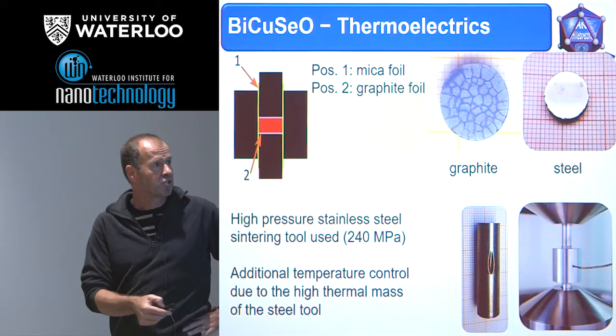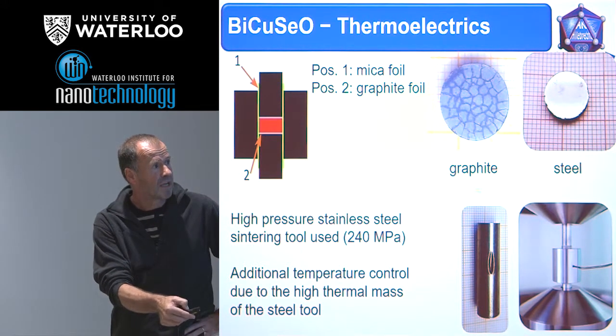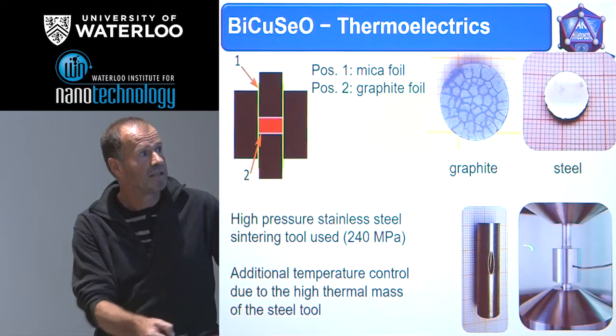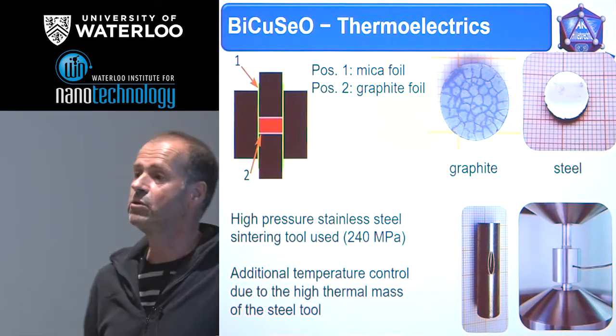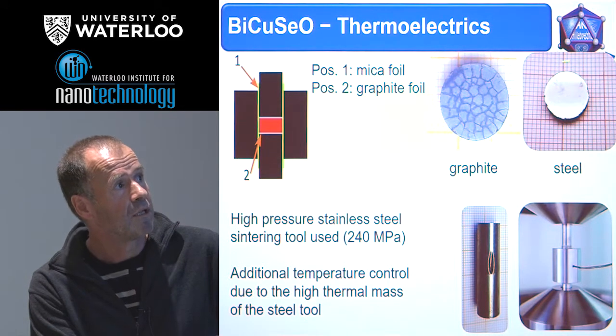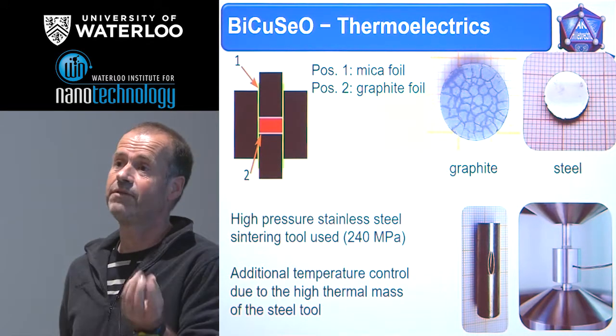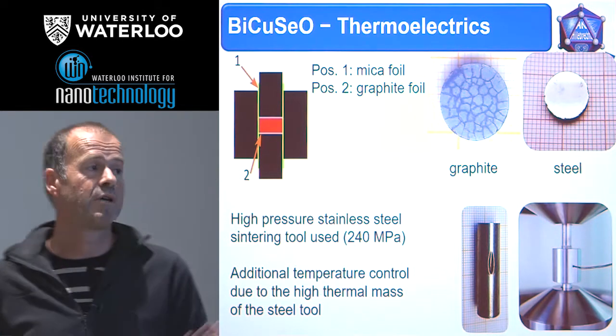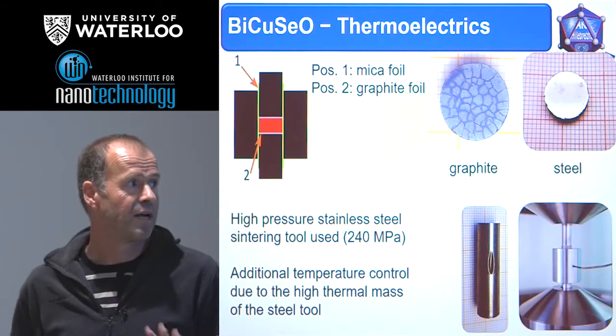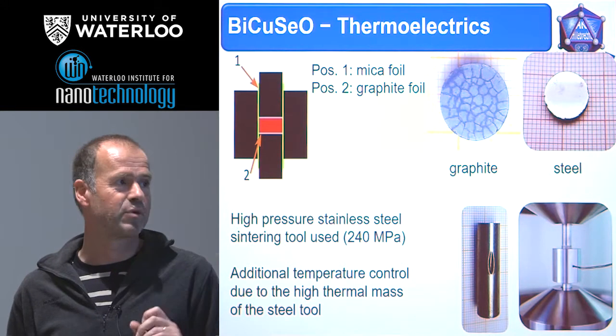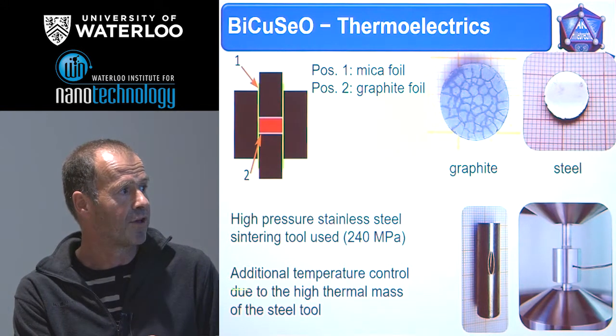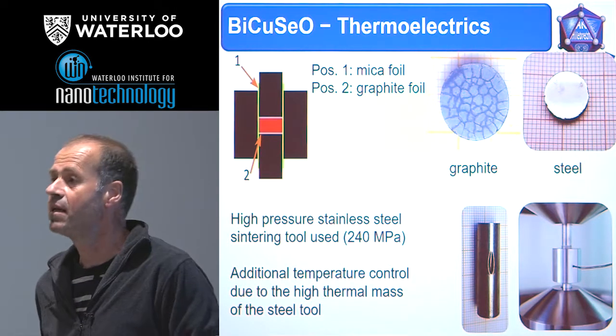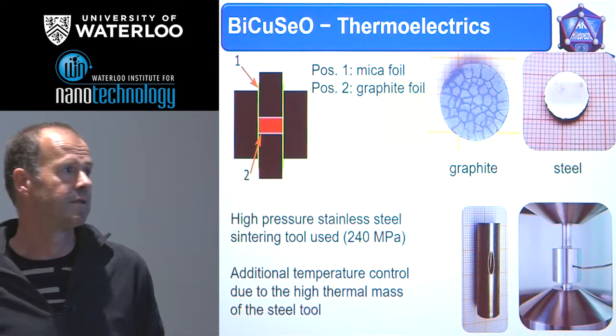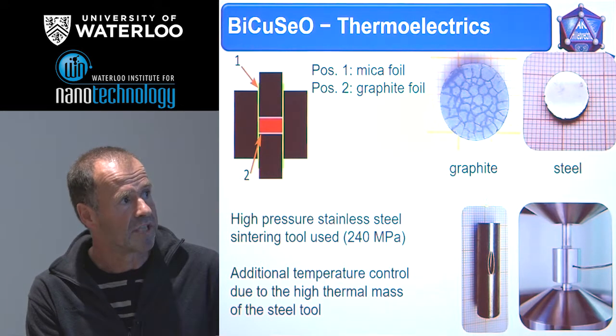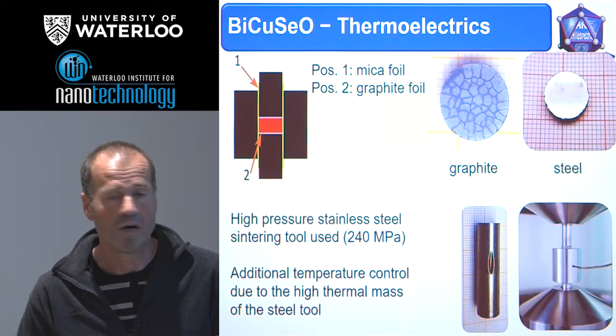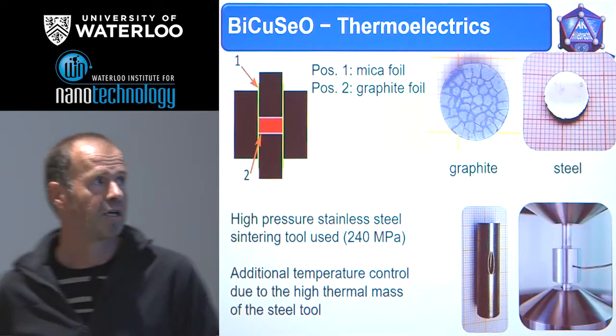But we have changed our pressure device from graphite to steel, and then we could apply a higher pressure. Using this higher pressure, we were able to obtain very well-developed samples where we could measure the thermoelectric properties. But it took some time to design the process in a new way to correct for the thermal mass of the steel, but now we are able to do it in a proper way. That means we could control the temperature by additional thermocouples, and now we are in a quite good way.